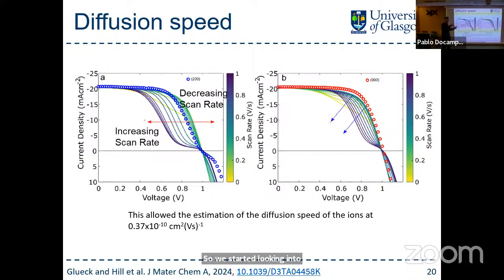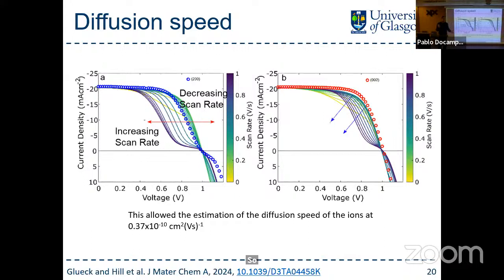So we have to work with the ions. What can we do with them? Well, the first step is what can it tell us about the physics of the system? We've already seen that depending on the position of the ions, you can get something that looks terrible to something that looks pretty good. That's changing the scan rate of my JV curve. So depending on the position of the ions, I get good charge extraction or pretty terrible charge extraction. So it's basically an indication of what is accumulating at one of the interfaces.